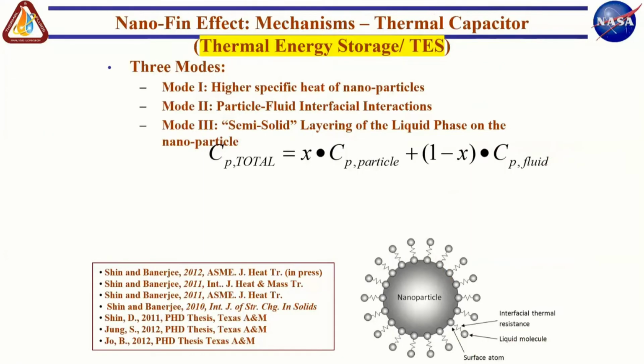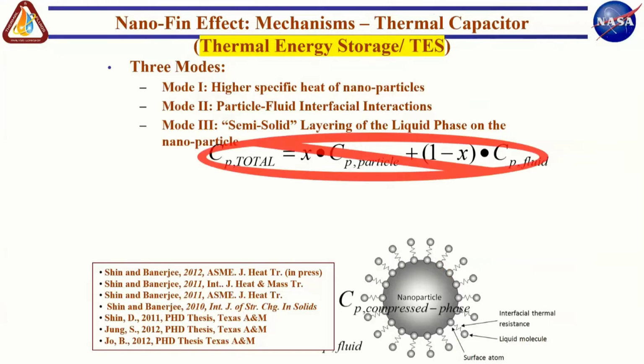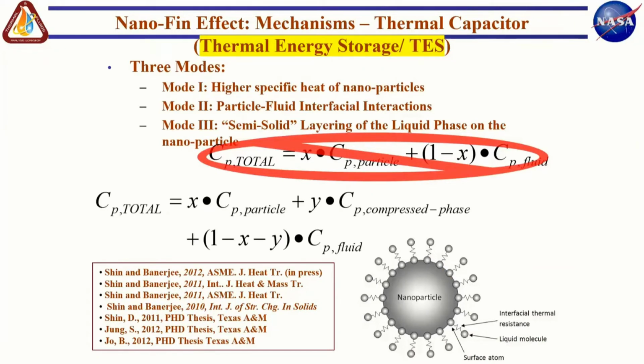So in other words, if you use the simple mixture rule, this is actually wrong, because this does not account for the compressed layer that forms around the nanoparticle. So the correct equation to use is, if I'm using 1% by mass of nanoparticles, which is your x here, times the Cp of the nanoparticle, then you can calculate the mass fraction of this compressed layer that forms around the nanoparticle. Let's say if it is a 2 nanometer thickness layer of compressed phase, you can estimate what this y will be, and you multiply it by the heat capacity of the compressed phase, which is typically the solid phase heat capacity of the fluid, or the solid state heat capacity of the fluid molecules, and then the remaining mass fraction times the heat capacity of the fluid. So once we use this equation, it matches the experimental data very well.